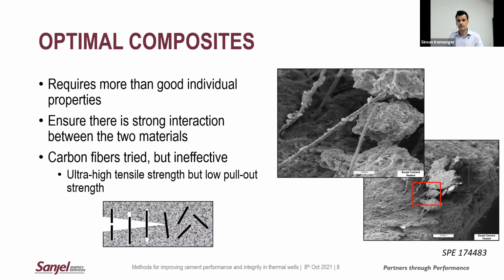Despite the fact that carbon fibers have ultra high tensile strength, certainly many orders of magnitude higher than that of cement, the surface chemistry wasn't compatible with that of cement. So we didn't get good bonding. And rather than the carbon fiber enhancing the strength of the matrix, it would just pull out, so we didn't get enhancement of those properties. That's really worthwhile paying a lot of attention to when you're looking at your graphene, your boron nitride, whatever it might be, to ensure you've got strong interactions there to maximize the potential.